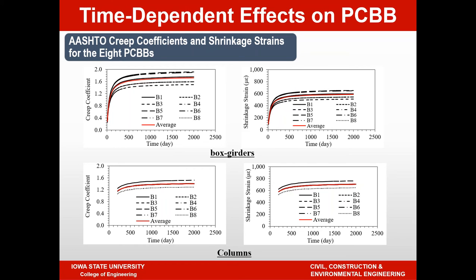And you can see the columns are older, and therefore the creep coefficient variation is smaller compared to the superstructure, where the superstructure creep takes place at very early stages because the pre-stressing is applied at the age of 7 to 10 days, when the concrete reaches its 7 to 10 day strength, whereas the column has been sitting in the field and may be as old as 200 days before the constraint is introduced, and that's what you're seeing, the difference between the two.